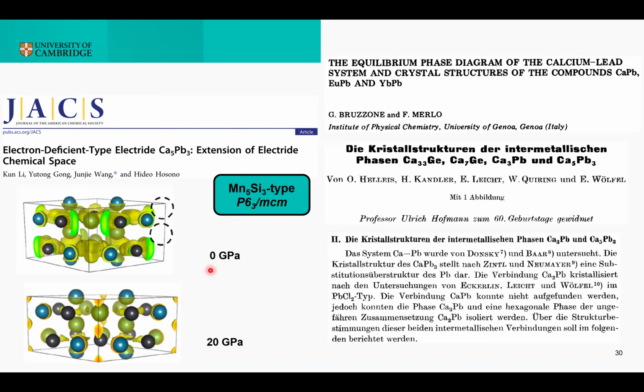I thought that was a very interesting case of study. However, this phase at ambient pressure is not an electride. The good thing is that the reason why I chose this system as a test case was motivated by this work done by Hosono and his group that predicted that squeezing this phase only up to 20 GPa, it would have undergone electride state transition. So that seems very interesting, and therefore I could check if my method could identify this phase and also accelerate the identification of these and similar phases.